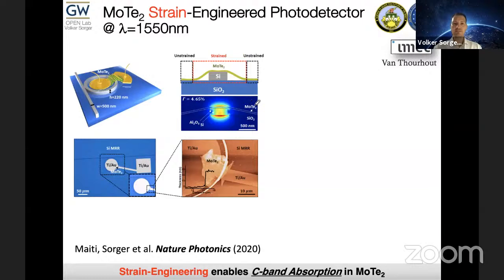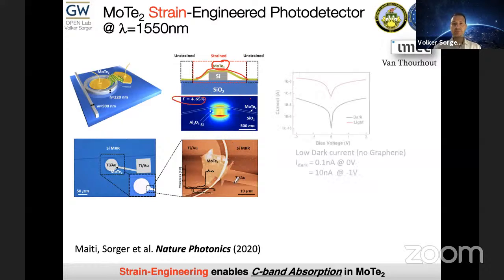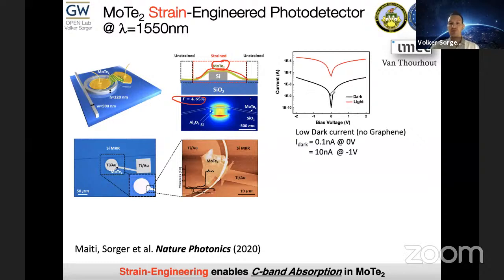This is shown here in more detail. So here's this wrapped-around structure. It's MoTe2. The overlap factor is about a few percent. Here are some images. If we do an IV curve, if we do not shine light at the structure, we have a pretty low dark current. It is about 1 to 2 orders of magnitude lower, actually even up to 3 orders of magnitude lower than for graphene, because graphene obviously has no band gap. So you always have basic carriers moving across. So this is a very nice low dark current.